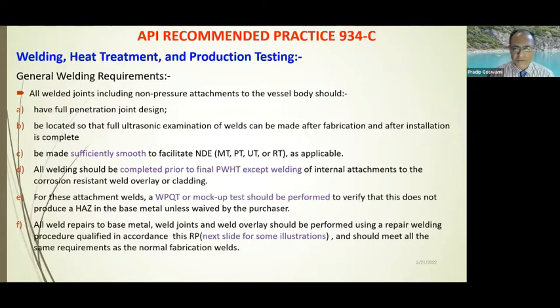Subject to the discretion of the client as well as the other engineers involved. And for these attachments, a mock-up test should be performed. For example, if these internal attachments are done after final post-weld heat treatment, this RP calls for a mock-up test to show that the welding of this internal on the overlay does not produce any HAZ in the base metal. So that means basically you have to control any welding heat input if you do the welding of this internal following the post-weld heat treatment.